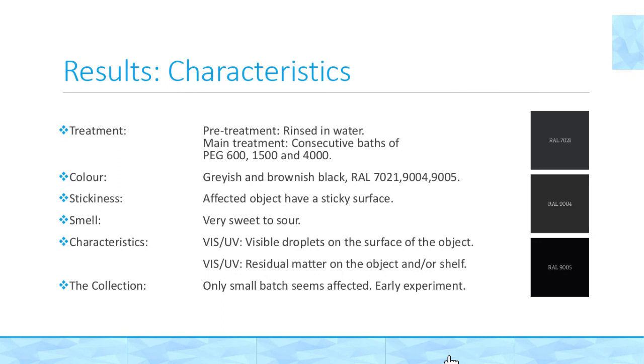In all cases, there were visible droplets on the surface of the object, both in visual light and when I used my flashlight. The same goes for the residual matter, both on the object and or on the shelf of the object. The UV flashlight made it possible to see the residue on the shelf, even if it was not visible in regular lighting conditions. Based on the treatment methods recorded in the treatment reports, I was able to conclude that only a small batch of objects seemed to be affected. I even found a source that actually stated that the above-mentioned treatment method was an experiment that was stopped in the mid-1970s because leaching was already observed back then.